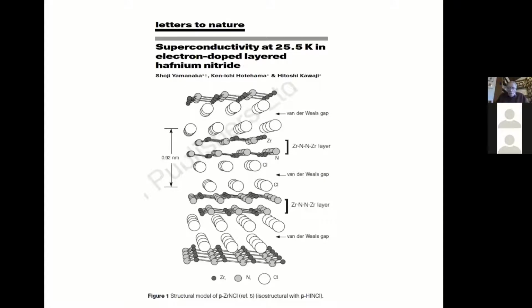There are other compounds that sort of fit into this scheme of things, which are surprising. Namely, you take zirconium nitrogen chloride. This is a compound where you have zirconium nitride layers, and you have chlorine layers here, which are essentially van der Waals bonded, and it's possible to intercalate in between various atoms.